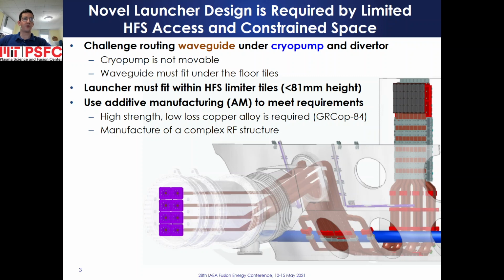A novel launcher design is required by limited high-field side access and constrained space. Challenging routing of waveguide, shown in brown, under the cryopump, shown in blue, complicates launcher installation as the cryopump is not movable, and the waveguide must fit under floor limiter tiles. Constraints on the central column require the launcher to fit under 81 mm thick high-field side limiter tiles, while disruption loads and a 400 Celsius bakeout prevent the use of oxygen-free copper due to annealing. Additive manufacturing from a high-strength copper alloy is used to address these design constraints.